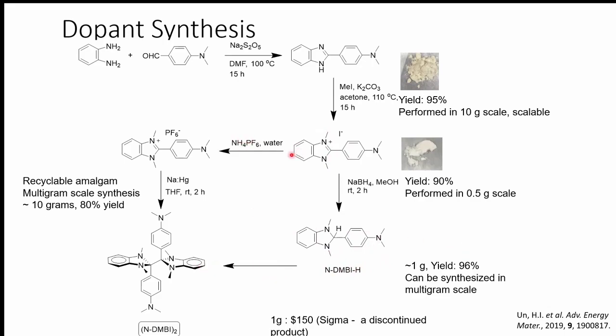Now, the other way to get to the dimer is that we need to change the counter ion to something more soluble like PF6, and then we use a sodium amalgam to reduce it and get the dimer. Although the sodium amalgam is expensive, it's very dangerous to use in the lab. You need to be very skilled, which thankfully I got used to after multiple failures. So I was actually able to recycle the amalgam, where you prepare a large batch of this and then react your organic, you remove your solvent plus the mixture, you keep the metal in there, and then you add fresh solvent, fresh compound, and then you do that multiple times till you've exhausted your whole mercury. Then you can either separate or add more sodium to the mercury and go all over again. So you're not generating mercury waste over and over again.